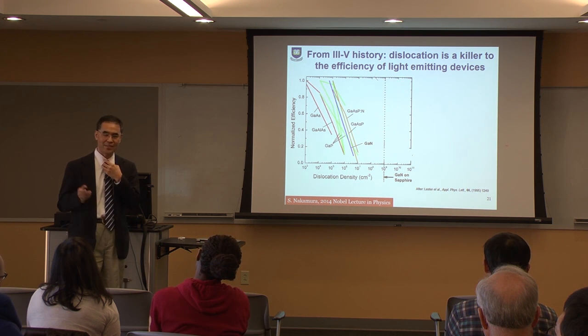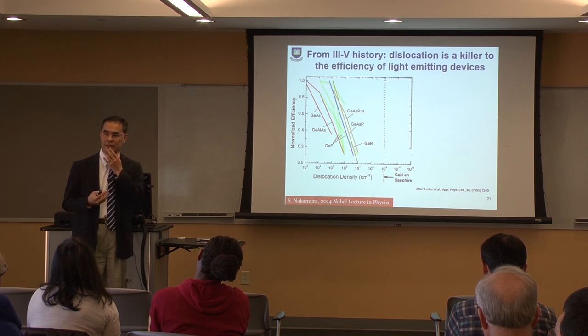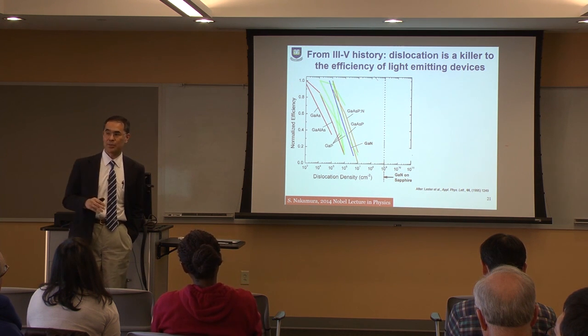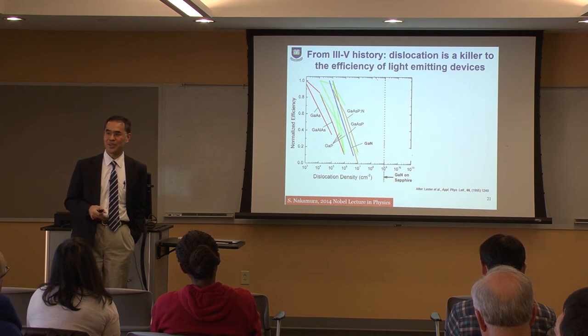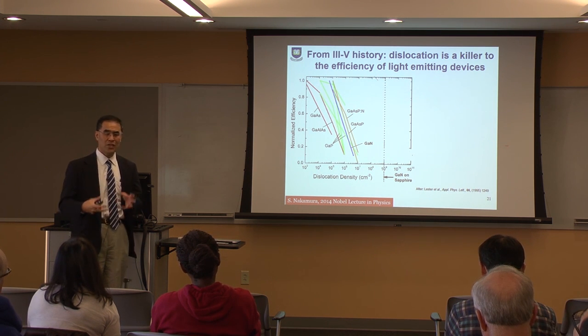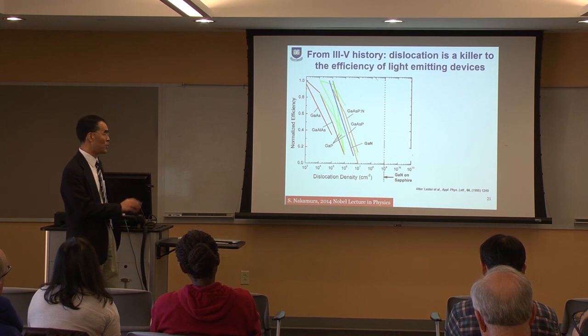Yeah, okay, thank you for asking. This is really a good question. Dislocations in gallium nitride are not that mobile. You need to heat it up to 1,300 degrees, and by the time you reach the temperature at which dislocations start to become mobile, as you correctly pointed out, you will lose the nitrogen from the surface. You need to find a way to cap or protect the surface. So that was the main issue. But presumably, if you anneal gallium nitride at a very high temperature, dislocations may glide, interact and annihilate. But at that time, it was not possible.